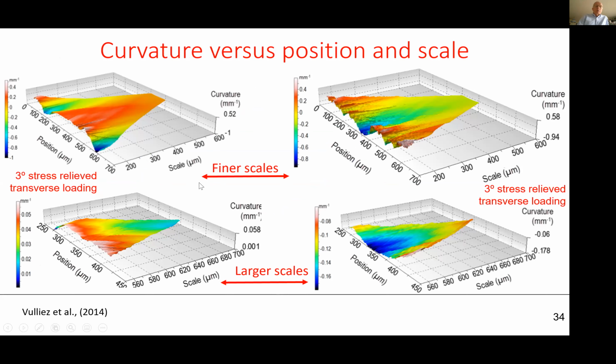Now here's a nice representation that Matt Gleason worked out. He's making these maps, and the curvature changes with color, as shown over here. So curvature is the inverse of radius. And as we get to large scales, the three heights that we use to characterize the surface get further apart, so we only get fewer curvatures near the middle. And here's the end of this one down here, which goes to one curvature that we can calculate reaching across the entire measurement.